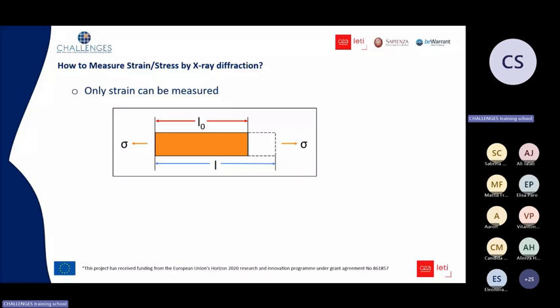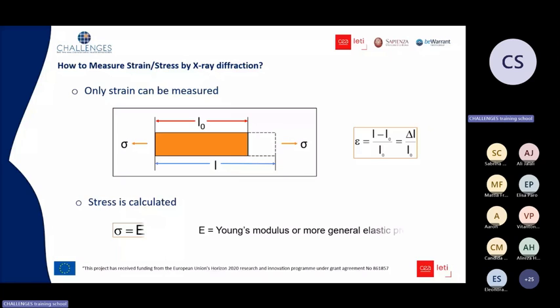So you measure strain, you can measure this difference of length, and the only way to get the stress is to calculate it from the elastic properties of the material. Here, in the simplest case of uniaxial stress, the relationship between the stress and the strain is the Young modulus of the material. But it can be more complex in the general case.